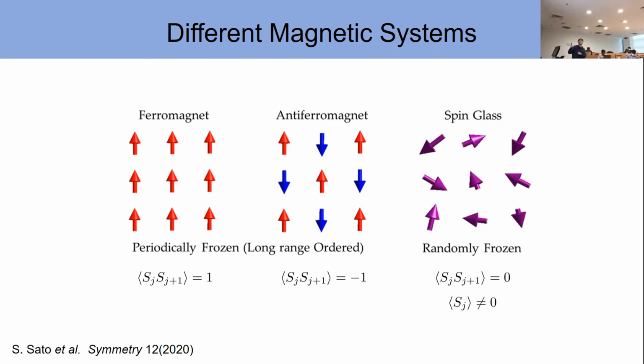However, there exists an exotic magnetic phase called spin glass, which is described as randomly frozen. This means that although there is non-zero on-site magnetization in a spin glass, you cannot predict the magnetization on other sites from this single site. This is mainly due to the frustration between the anti-ferromagnetic interaction and the ferromagnetic interaction. As a result, the spins are just randomly oriented, just like a glass.